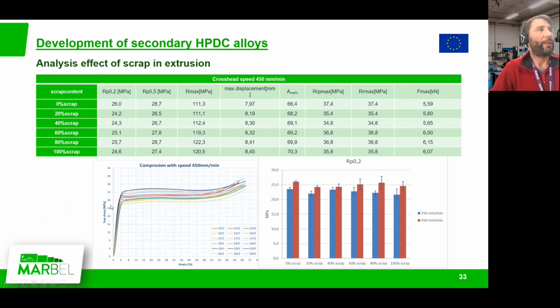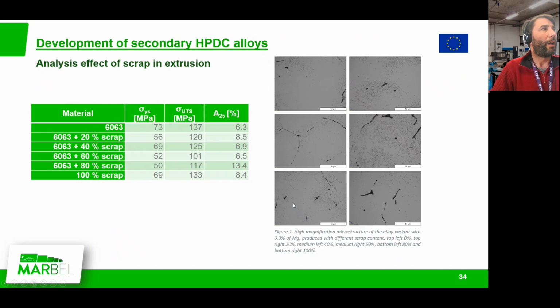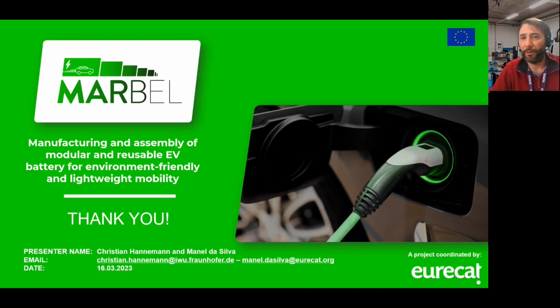And we also analyzed the effect that it will have on the formability of the alloy. For high pressure die casting, we analyzed fluidity. Here we analyzed compression tests at different temperatures and different speed rates. And also the impact is minimum. So the impact on formability, on extrudability of the alloy should not be very large. And in terms of mechanical properties, we also didn't observe any clear trend regarding the impact of scrap on the mechanical properties. And well, that's all from my side.